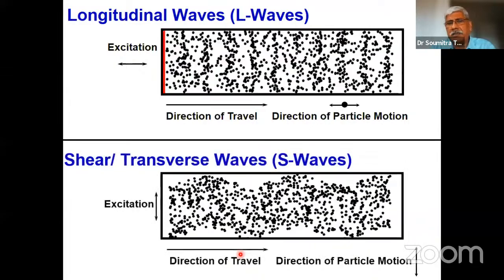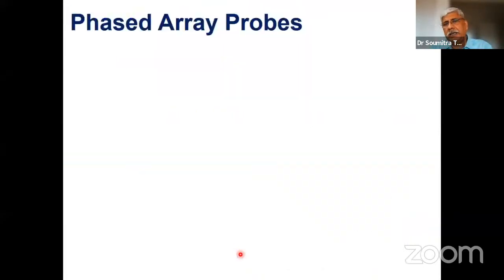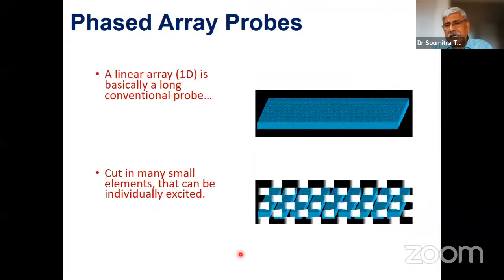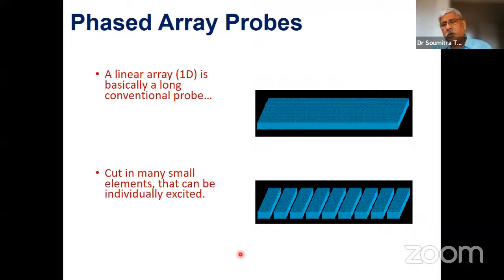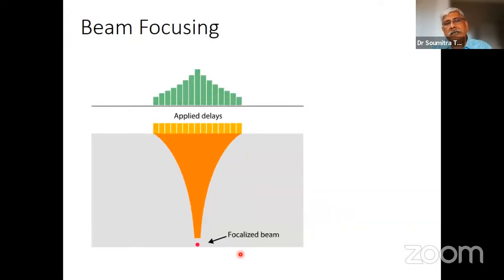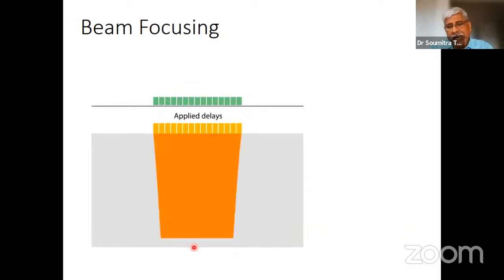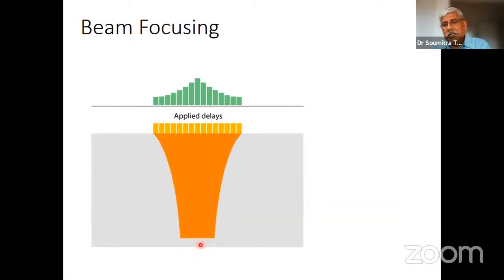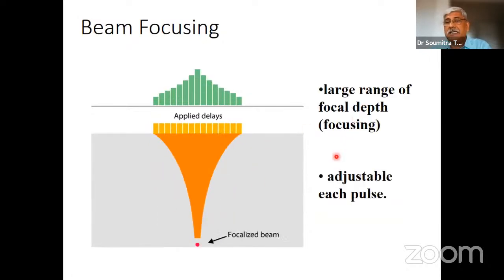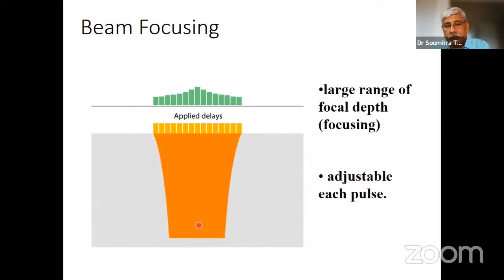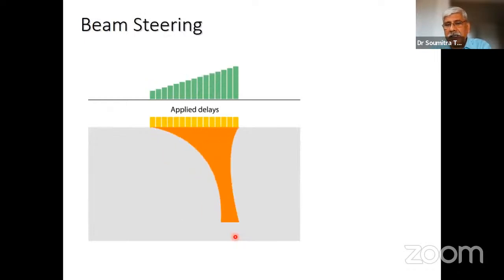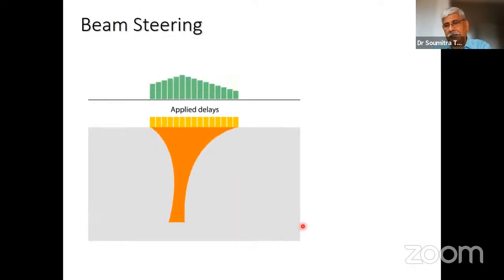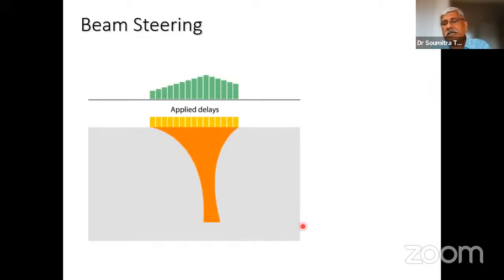You can use longitudinal waves, shear transverse waves, or combined waves to probe a material. You have these phased array probes, which are essentially a piezoelectric probe which has been cut into small bits, which can be triggered and which can be used for receiving in different phases, different phasal configurations electronically. And through that, you can actually focus a beam, ultrasonic beam, and look at a particular area. You can also have a very large depth of focus and adjust each pulse to check various locations. You can also steer that focused beam to look at a sector, to find out where a defect is and what is the extent of damage.